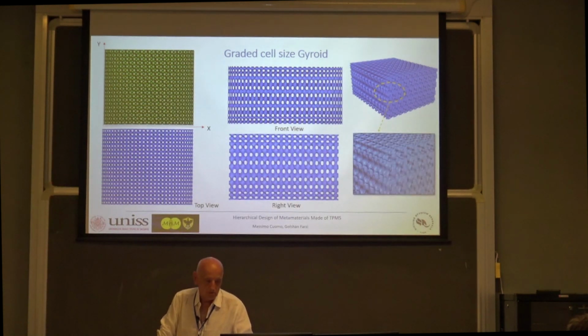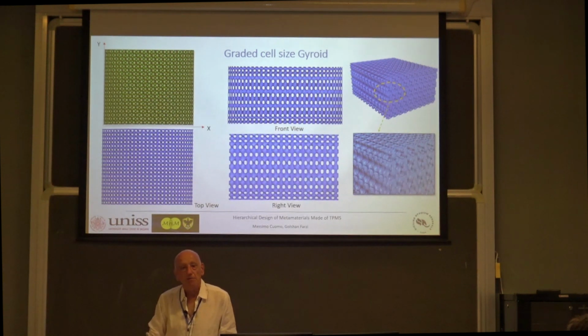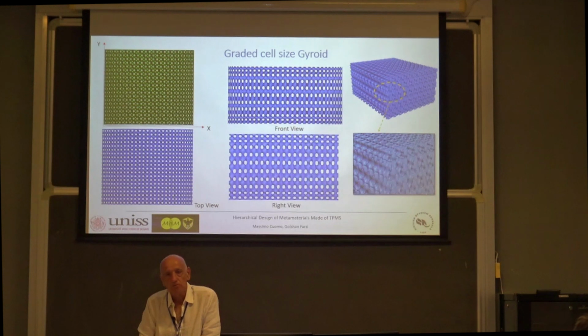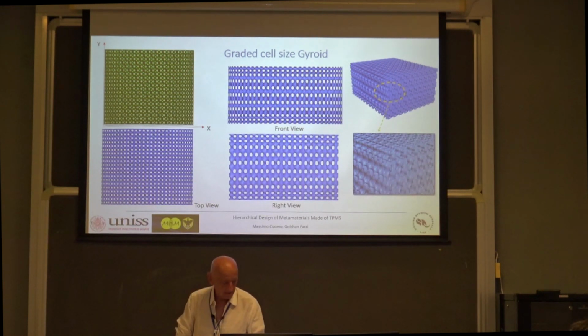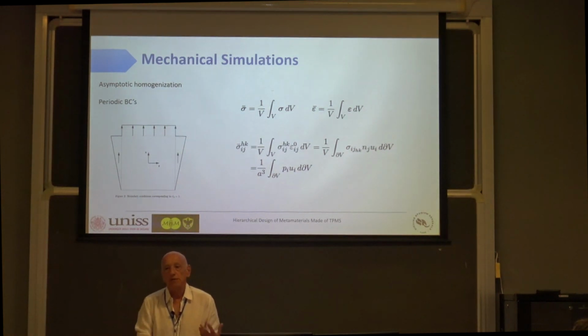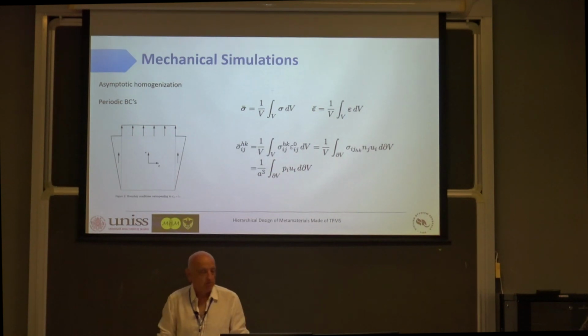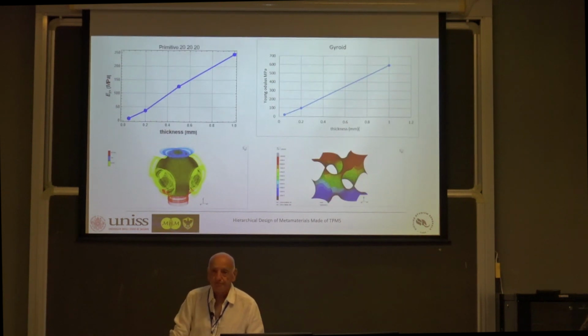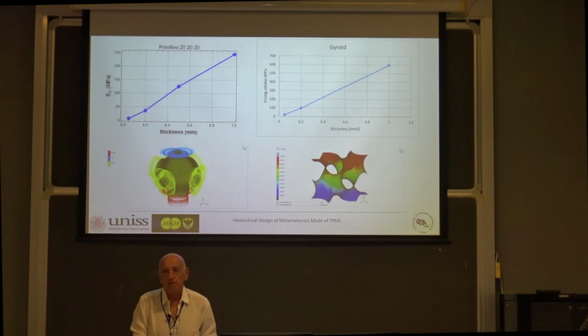Now, imagine we want to make a mechanical analysis on this structure. We need some 6-7 million elements to make a reasonable interpolation of this surface, which means a very heavy task, especially if you want to make nonlinear mechanical analysis. So the idea is to use asymptotic homogenization, obviously, with periodic boundary conditions to obtain the homogenized properties. It is very standard, and I will show some results of this homogenization.